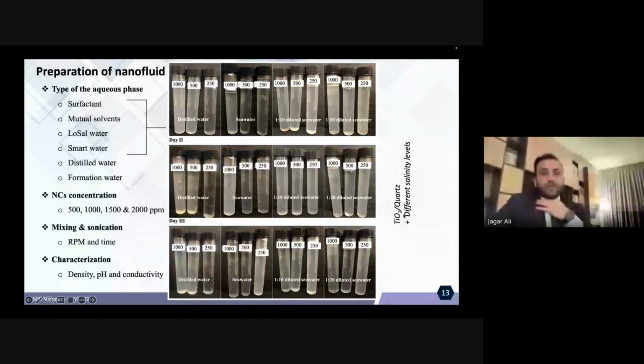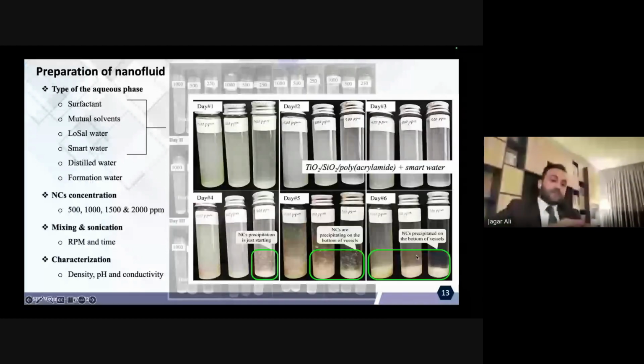These are some pictures of the nanofluids, different nanofluids. For example, this one is the dispersion of TiO2 quartz with different salinity levels of water. And by leaving these nanofluids for 3 days, we still can see a good dispersion stability. Dispersion stability is very important because when we inject the nanoflow inside the porous media, nanoparticles should remain stable, dispersed inside the water. And if they are not dispersed, it means they will not be effective and they will be lost inside the porous media.